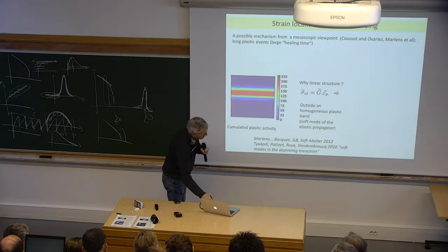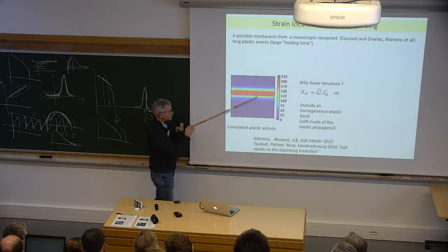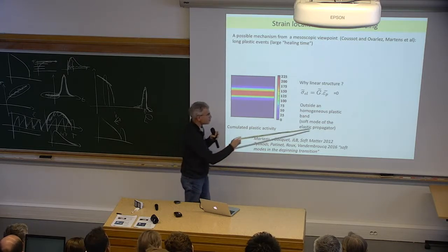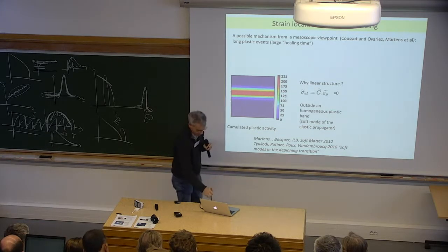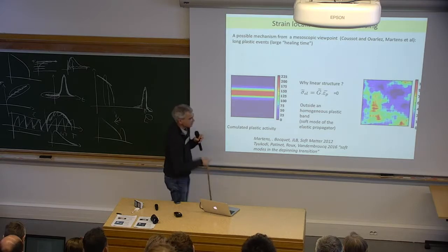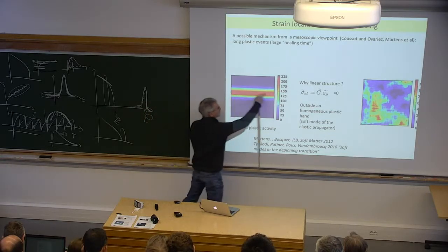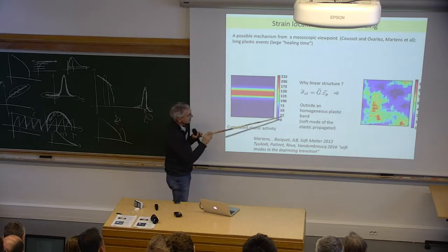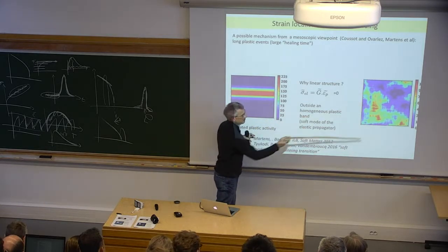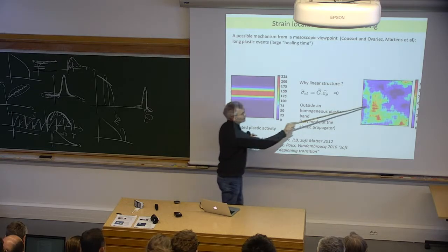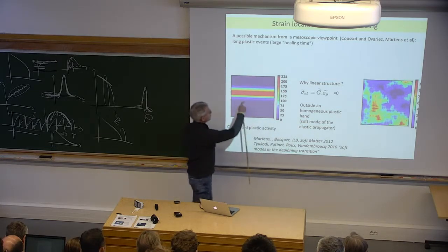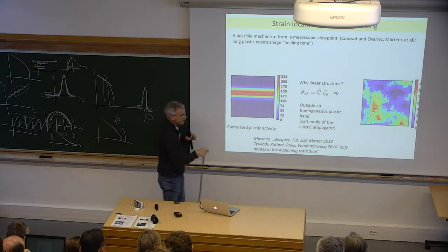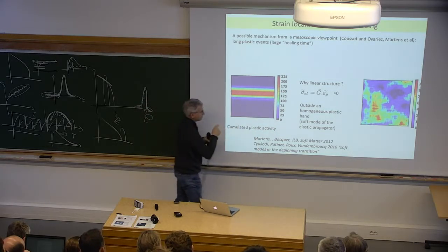An interesting point here is that in order to observe this localized band, it's not enough to have this long healing time. It's also important that you use the proper elastic interaction. If you use an interaction between sites that doesn't have this soft mode, these horizontal modes as an eigenmode, then you find something which is localized but very transient. You have patterns of plastic activity, but they remain very transient and do not organize in the form of a shear band. This suggests that if you introduce disorder in the elastic propagation, then you will actually stop the propagation or the establishment of the shear bands.